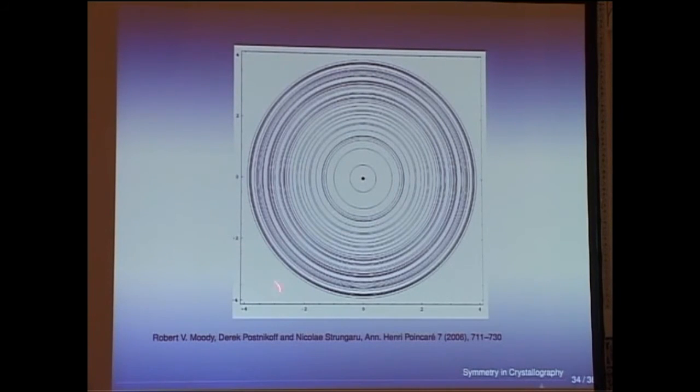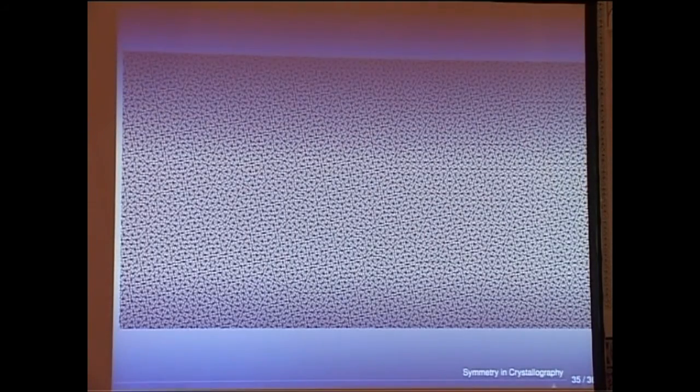Mathematicians very recently have proved one thing. It's Moody and others at Henri Poincaré. They have proved that the diffraction pattern should be perfectly isotropic. By the way, can you imagine, this object I am showing you is the most perfect powder diffraction we can invent. It's perfectly isotropic, it's made with one unique triangle, there is only one kind of triangle in it, it's perfectly coherent everywhere, it fills the space, and it fills the space isotropically in all of two-dimensional space. So I really wanted to have an idea of what the order was there, because everything I've told you until now just fell down.